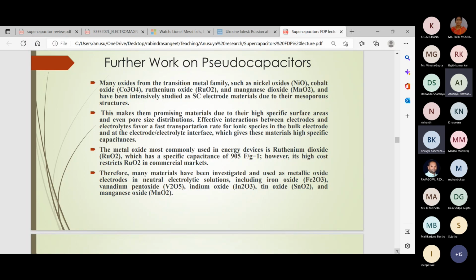When you heard that, what are these electrodes? There are many oxides from the transition metal family which are used: NiO, manganese dioxide, cobalt oxides, ruthenium oxide. Ruthenium oxide is very much used because it has a huge specific capacitance of 905 farad per gram. But have you ever heard of ruthenium in a chemistry lab? No, because it's a really rare metal. So even though it's got such good performance metrics, often it is not really used. Because of the money, it's got a very restricted use.